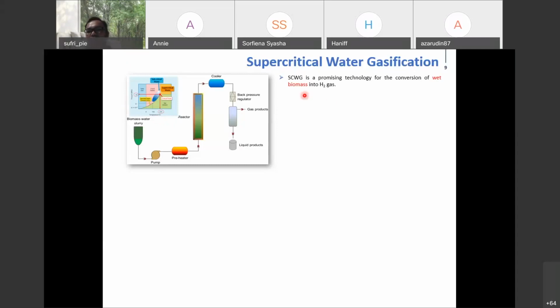Remember, biomass normally contains a huge amount of moisture. This is the main problem when we use biomass as the feedstock. In this technology, we use supercritical water as the reaction medium. So we need no pre-drying treatment for the biomass, because we mix the biomass with the supercritical water. However, in conventional gasification, before we start the gasification reaction, the biomass has to be dry.